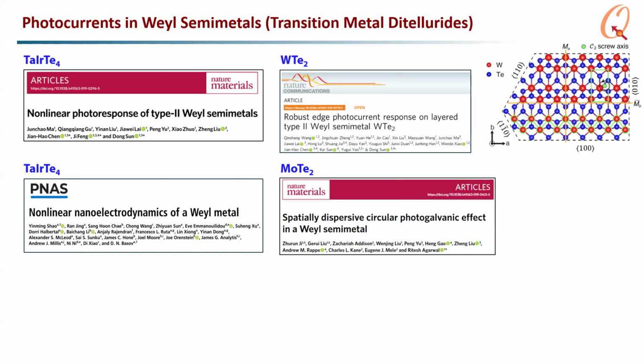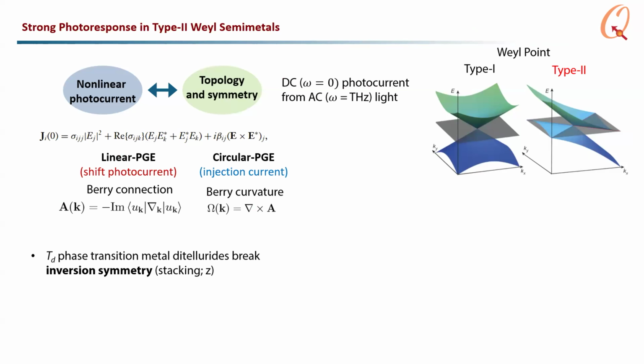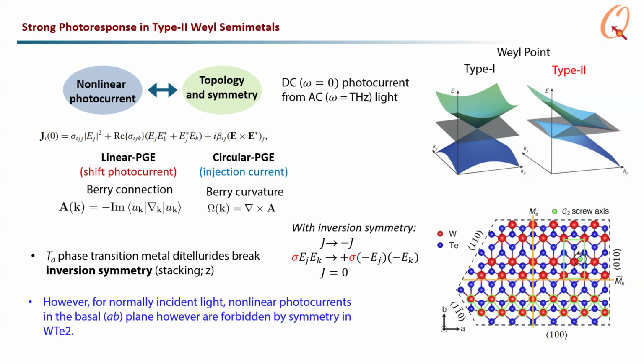So we wanted to use these techniques because we were interested in photocurrents in Weyl semimetals. There was a lot of work, maybe 3 or 4 years ago, on these transition metal ditellurides, saying that an enhanced photocurrent was observed due to several effects. Why were people looking at these transition metal ditellurides? It is related to the physics that Joel Moore was talking about, in that these materials have Weyl points, actually type 2 Weyl points, and they break inversion symmetry. So they should be host to a nonlinear photogalvanic current that's related to the topology of the Weyl points. In particular, Weyl points have divergent Berry curvature, so you might think that they would have a particularly large response for this nonlinear photocurrent.